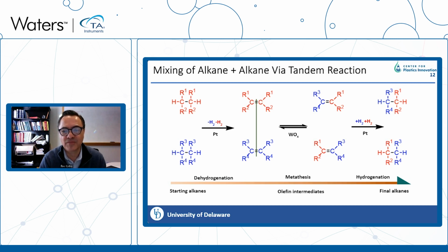We'll combine the pieces of these olefins into new olefins as indicated here toward the right. And then we are going to use again the platinum catalyst to return the hydrogen that was removed at the beginning and transform the olefins into alkanes. So we start with alkanes and we end with alkanes, but we produce in the process a small amount of olefins that are the ones that are really reacting and doing what we want, which is to reduce the molecular weight of the polyethylene.